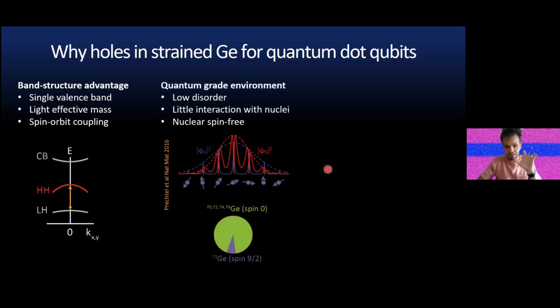The second reason is that these quantum wells offer a really quantum-grade environment in terms of electrical disorder, because these are buried channels. You are far away from the nasty oxide interface. By working with holes and not electrons, the wave function has very little overlap with the nuclear spins, which are a main cause of decoherence. And eventually you can even get rid of the nasty nuclear spins, which in germanium are the spin 9/2 from germanium-73.